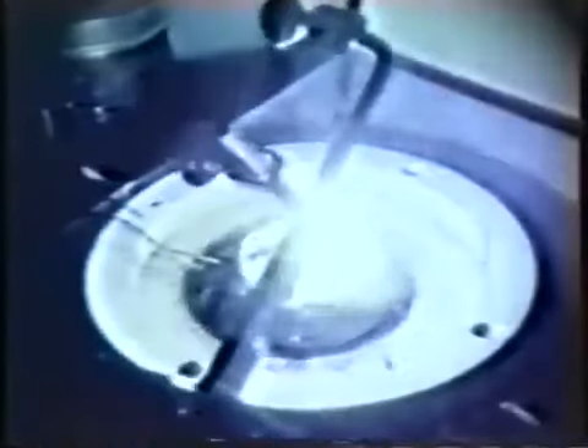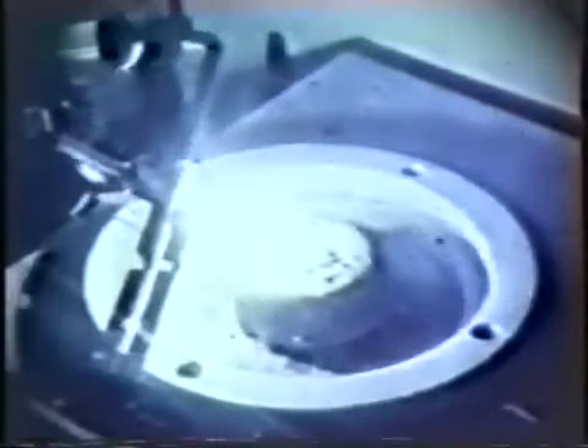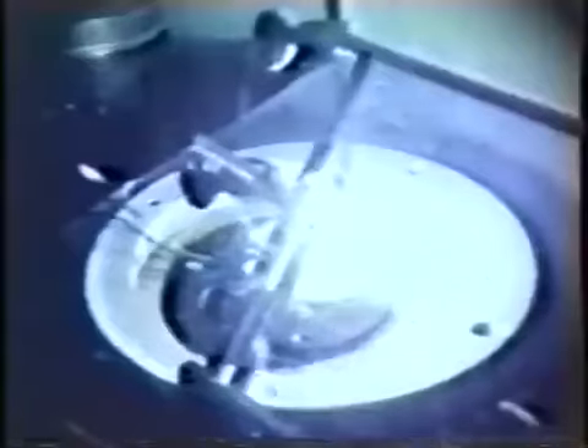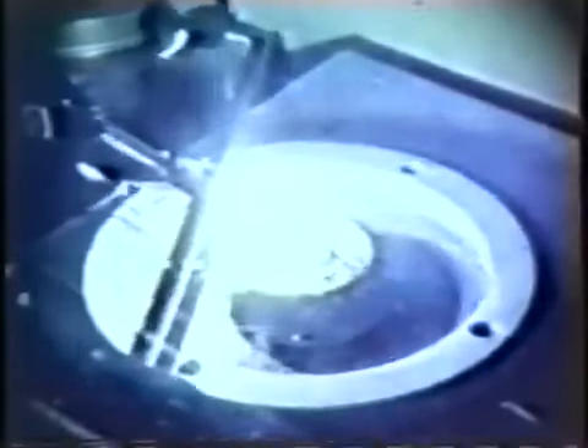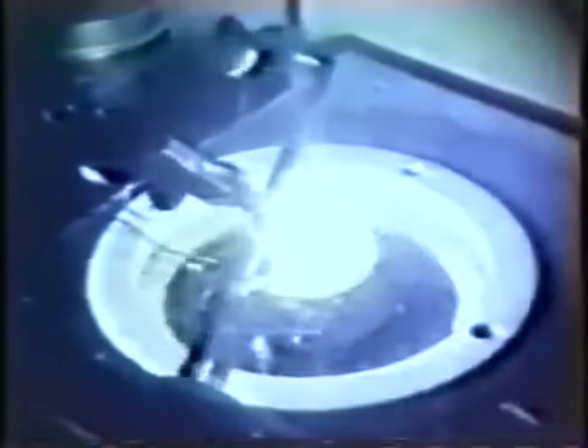In order to ignite this larger piece of plutonium required a carbon arc torch, doing away with the notion that large metal buttons would ignite spontaneously or with a small amount of heat. We actually had to go several minutes of heating with a carbon arc torch before the metal would ignite. It burns somewhat like a charcoal briquette. It ignites on an edge and slowly transmits the heat to the whole button, and pretty soon the whole button is burning.